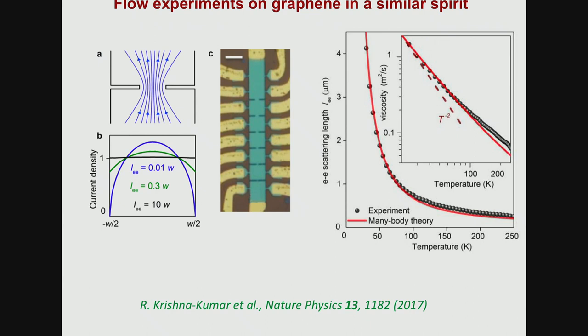Now, there's always assumption. Everybody's experiment is measuring a signal, analyzing it with a theory, and then coming up with some claim. One of the really impressive things that they can do in Geim's experiments, though, is that because they're working at density levels where they think electron-electron scattering is absolutely the dominant source of their hydrodynamic scattering, they can back out the electron-electron scattering length from the analysis and plot it as a function of temperature. And they did not just a total Fermi liquid theory, they did a Fermi liquid theory with some corrections, and they claim, but anyway, even so, what they are seeing is the electron-electron scattering length diverging not so far from 1 over T squared, and that is exactly the divergence that was seen in the viscosity of helium-3 right back at the beginning of the first part of the talk.